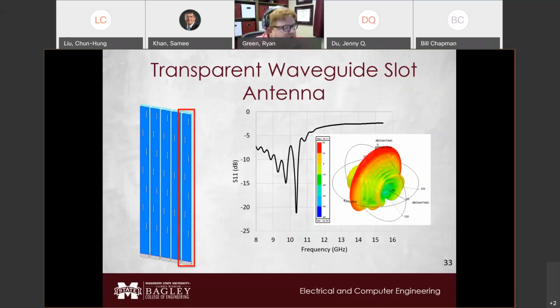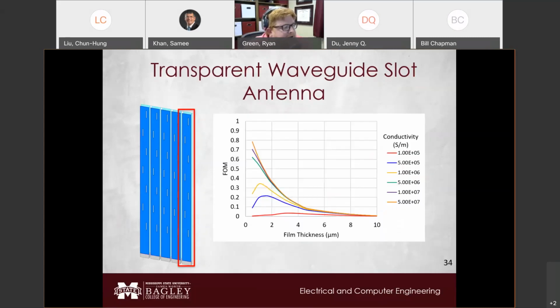And then what we took a look at was the figure of merit. What we see here is very similar to what we saw with the other antenna, which is essentially: make it more conductive and you'll get a better figure of merit. But what we find is that this maximum level is a lot lower, and actually closer to 1.5 micrometers than anything dealing with the other antenna designs. So we're going to be moving forward with this hopefully over the summer and the next semester, and seeing how it works in the real world.